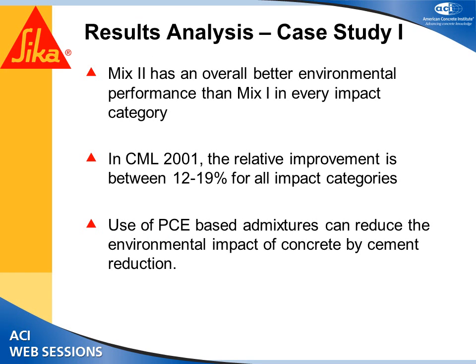Based on this case study, it was found that mix 2 had an overall better environmental performance than mix 1 in every impact category. In CML 2001, the relative improvement is between 12 to 19% in all the impact categories, and the use of PCE admixtures can reduce the environmental impact of concrete by cement reduction.